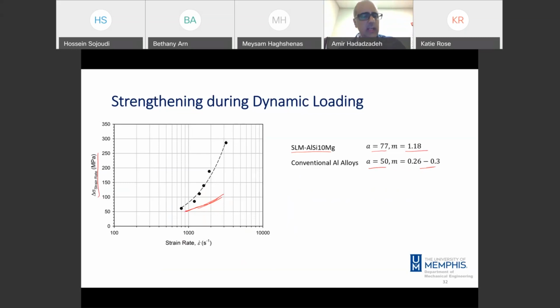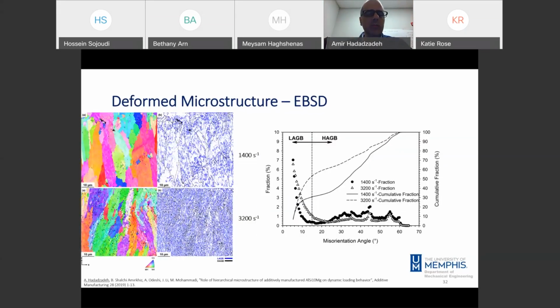and again, the reason for such a difference is the hierarchical microstructure. I looked at the grain structure of the material using EBSD in two different deformation regimes at 1400 per second and 3200 per second. As you see, the deformation in the single peak regime resulted in evolution of a discontinuous low angle grain boundary network in the structure, the blue lines in here. By increasing the strain rate, those networks developed, and now we have a well-developed continuous network of low angle grain boundaries.